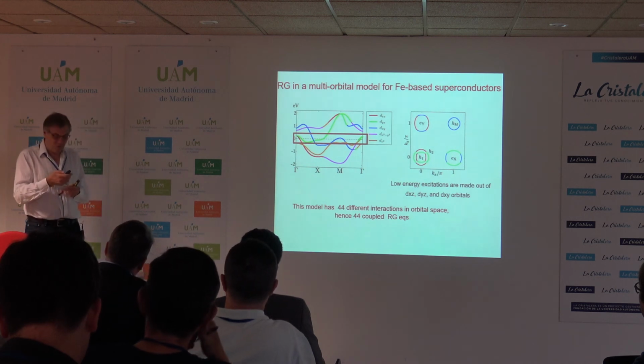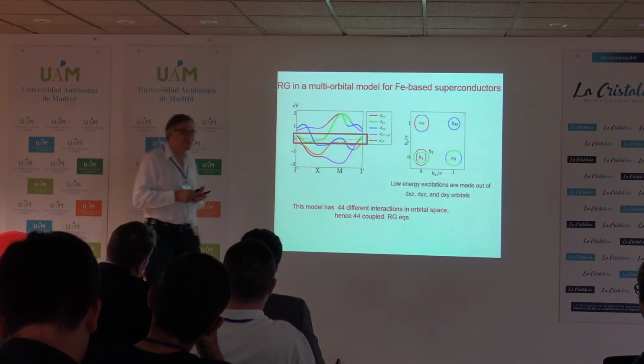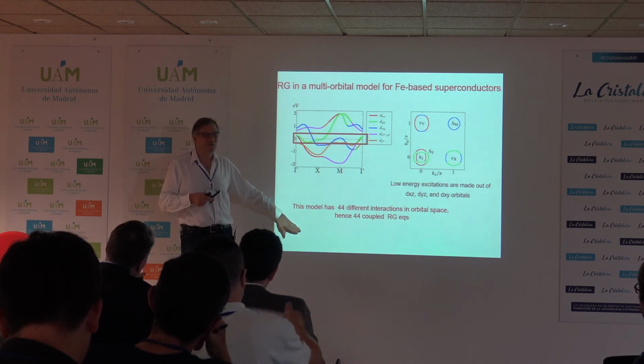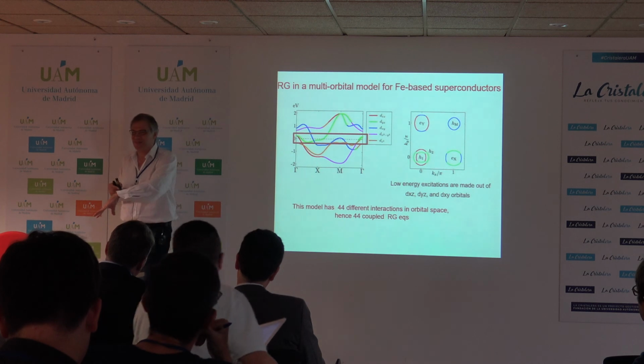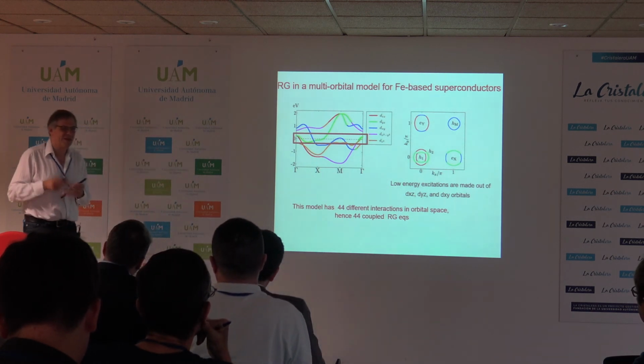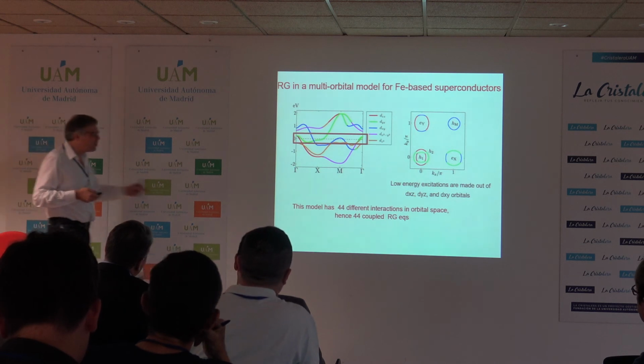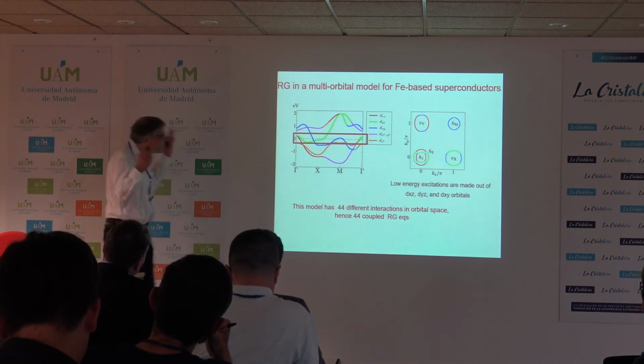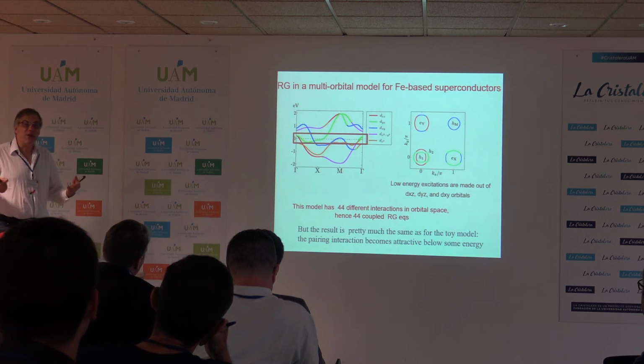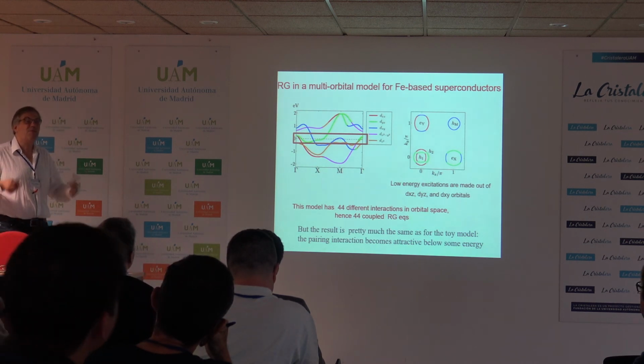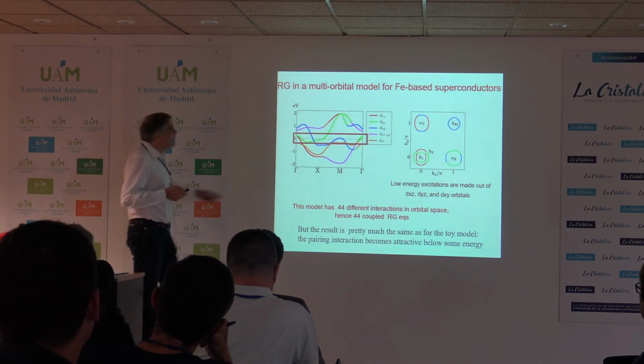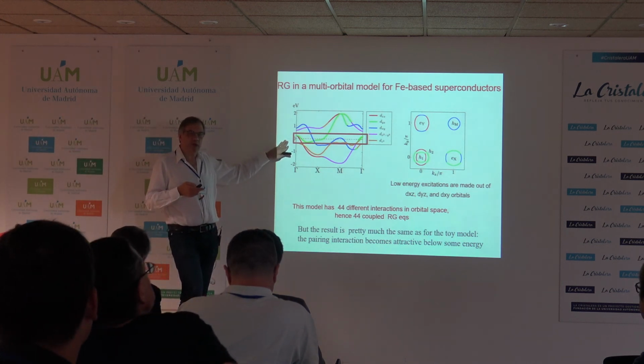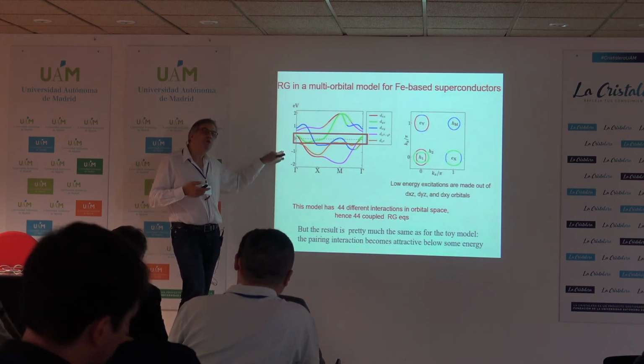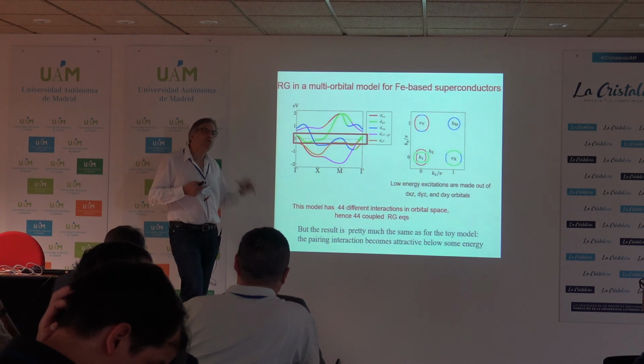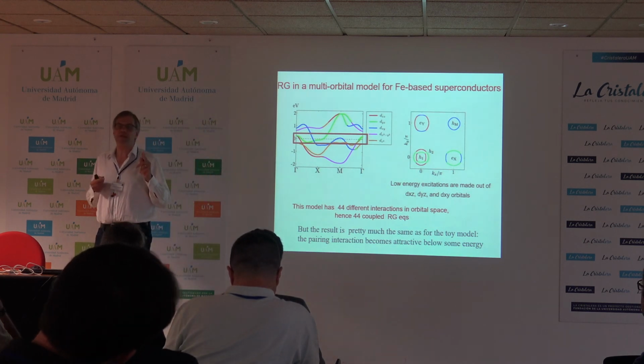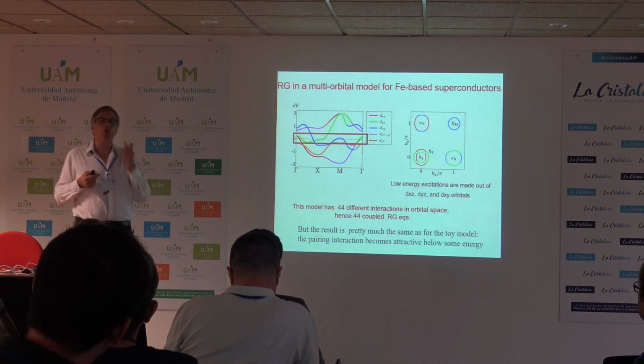And we really wrote 44 analytical RG equations, but I'm cheating a little bit here, because out of this 44, you immediately find out that a pretty large number, 30-something, can be eliminated because the corresponding couplings flow to 0. So it's not really as difficult as it looks, but it's 44 couplings anyway. But the end of the story is exactly the same as I told you in the simple case. Spin fluctuation promotes superconductivity. There is, however, one more interesting part of the story. It turns out that if you include orbital content, spin fluctuations promote two types of interactions. They promote superconductivity, and also they promote interaction that leads to orbital order.